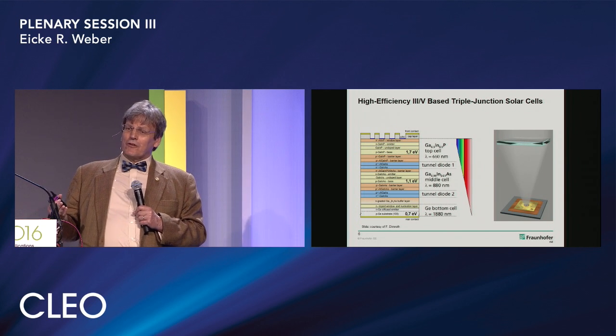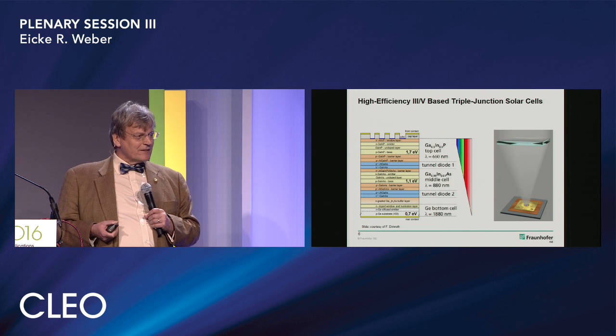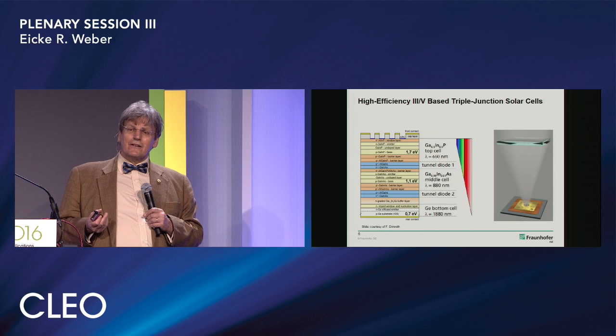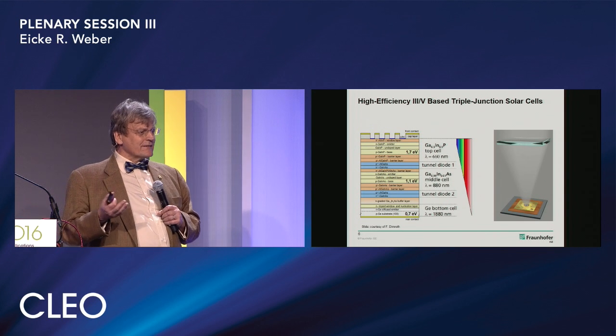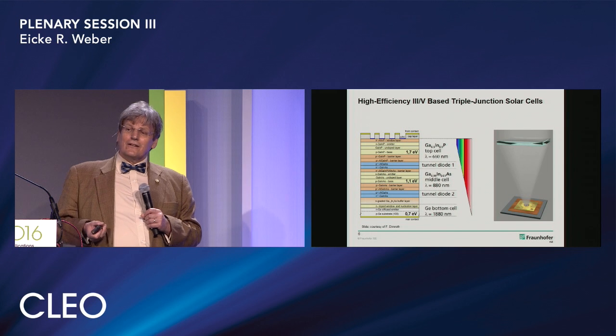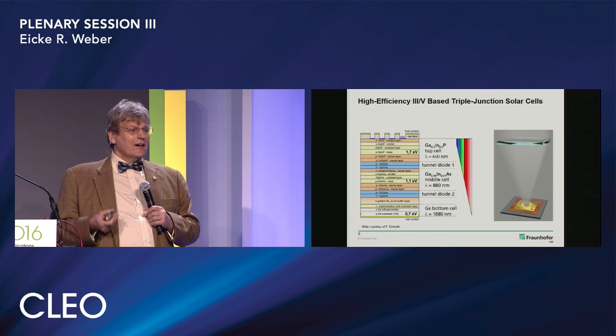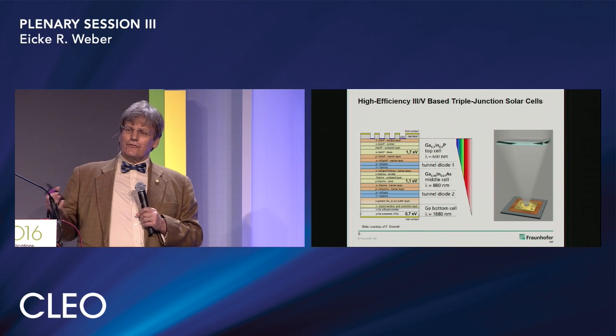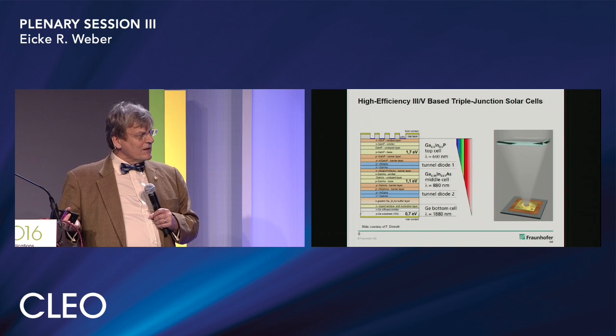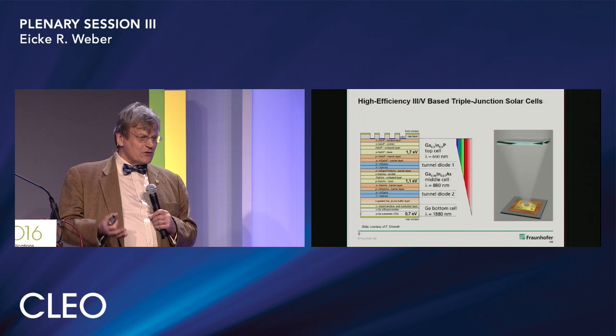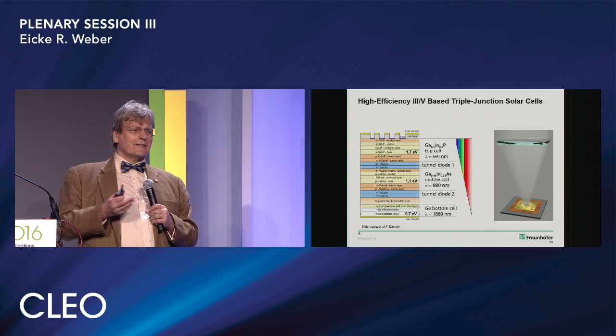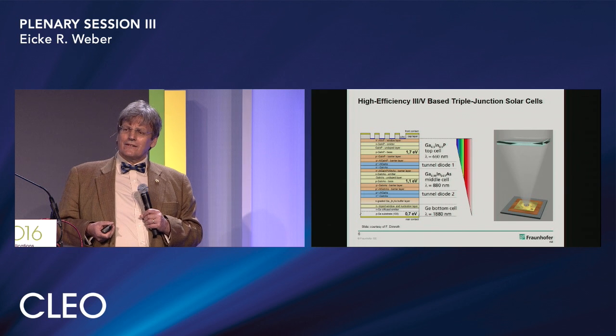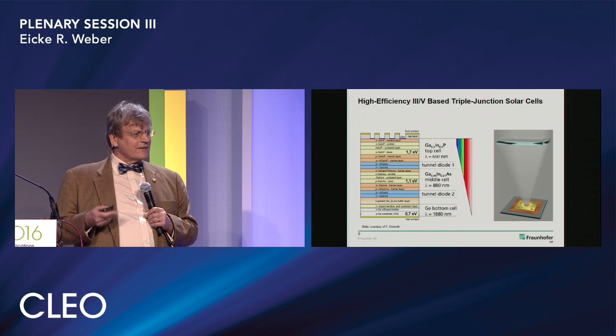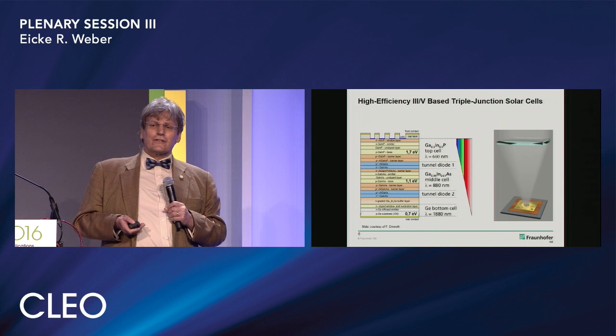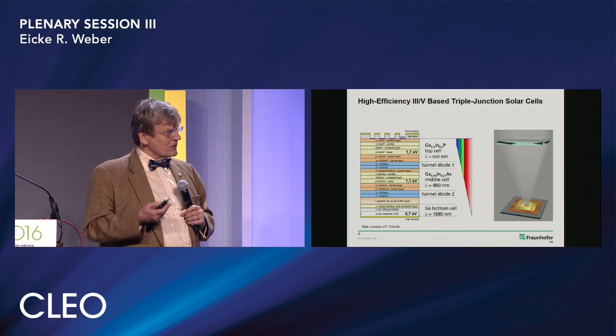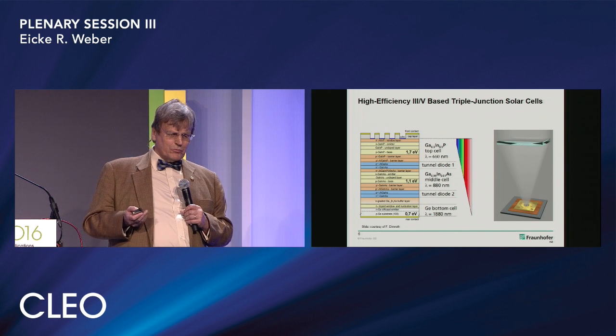Physics helps us because the number of recombination channels in each given material is limited. And therefore, if you use only one sun without concentration, these recombination centers can be quite dangerous. But if you concentrate 100, 300, 500 suns, then the recombination channels are bottlenecked. They cannot efficiently recombine as many carriers as they could do in relationship to the carrier density in one sun. So the efficiency of solar cells increases with concentration, and therefore this technology not only is needed in order to make cost-efficient modules, it helps as well boosting up the efficiency.